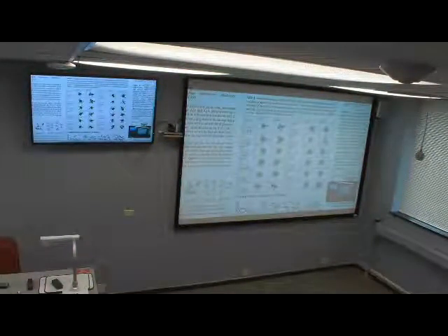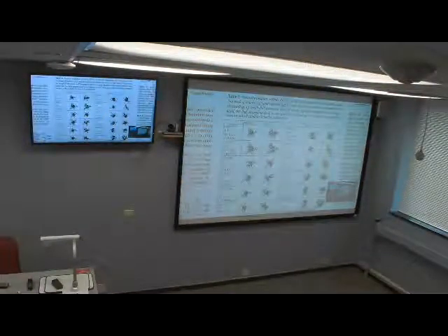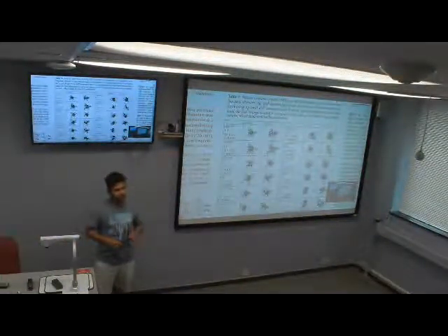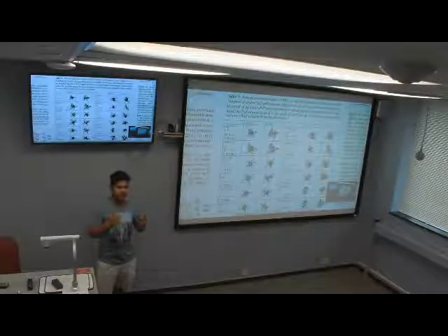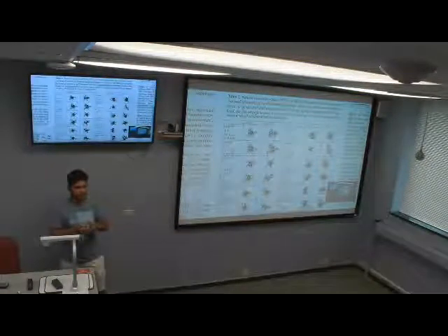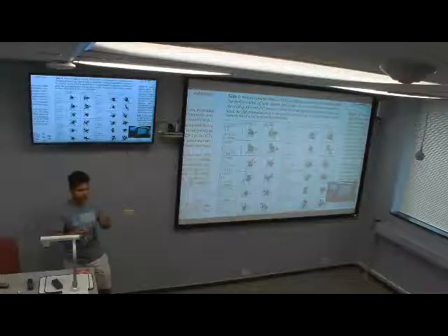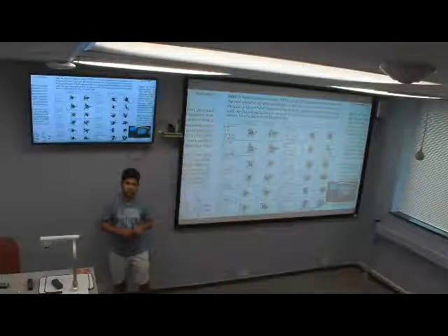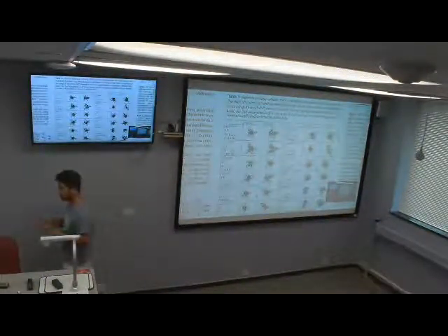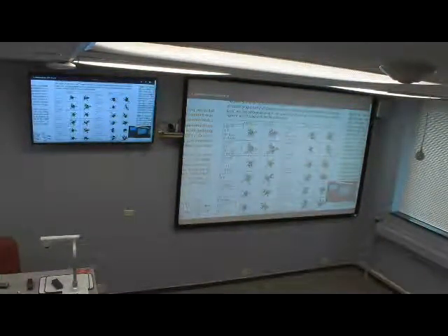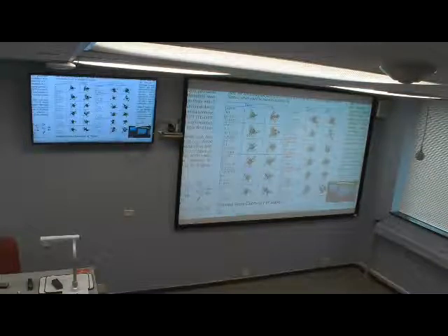Also, since they are not sure about their conformation, there is some other support from the literature and experimental work that silver cluster formation is initiated by silver plus, and the silver plus cations agglomerate and make a cluster. So almost all experimental results support that the final silver cluster could be positively charged, not neutral. So our silver 6+ shows more agreement and is also a cationic cluster, so we assume it could probably be the stable cluster in this case.